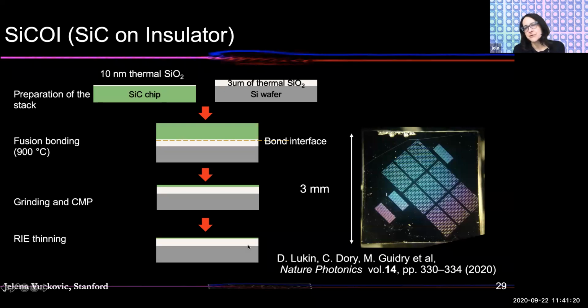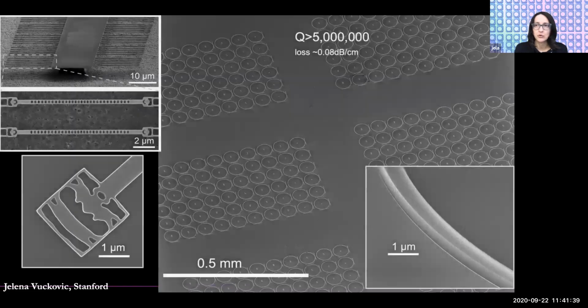Before we did this, we also tried smart cut, which relies on ion implantation, which is what people use to make silicon on insulator, but that really didn't lead to high quality material, because you bombard material with ions, and that leads to unintentional defects inside of the structure. So that's not good for quantum optics in particular. And also for classical photonics, it degrades the properties of the interfaces.